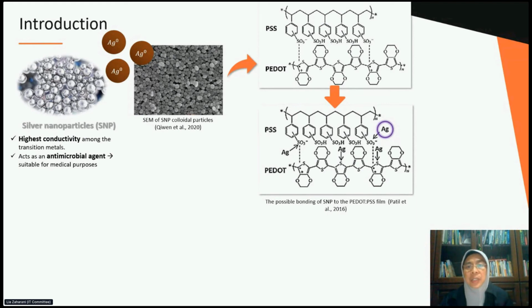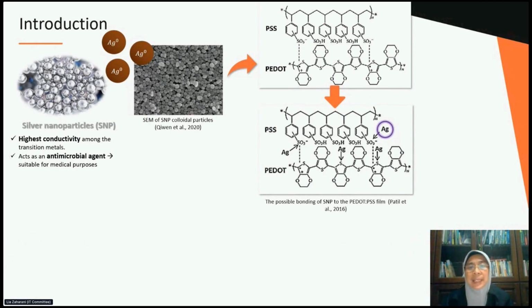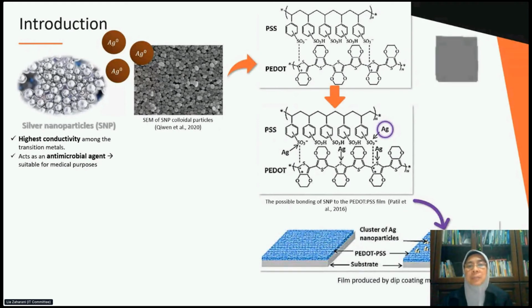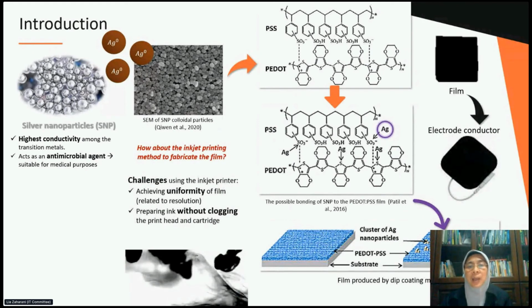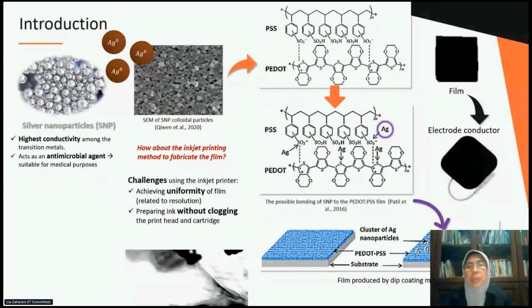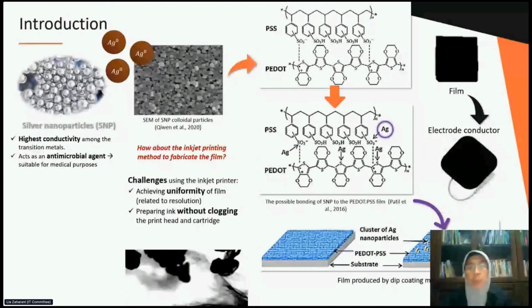So the typical particle shape of the SNP is spherical and it is able to provide inhibition of microorganisms and bacteria. So the possible bonding between the PEDOT:PSS and SNP has been established, where the SNP attaches to PEDOT chains and balances the counter ion from PSS. Yet, the spherical shape of the SNP might clog the print head and cartridge nozzle due to agglomeration of particles, even though the SNP is claimed to be homogeneously mixed with PEDOT:PSS.